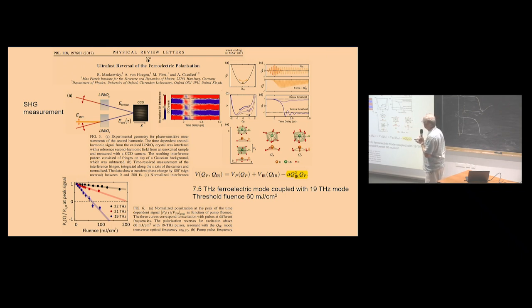When they pump it with terahertz frequencies, if they used pulses above 20 terahertz, they somehow reduced the polarization, but it was not switched completely. But when they pump it with 19 terahertz, they finally got the switching of polarization from plus to minus. And this 19 terahertz corresponds to the highest frequency mode which can be excited by this terahertz. So again, here is this quadratic coupling of infrared modes with another mode, which is responsible for such a change of polarization.